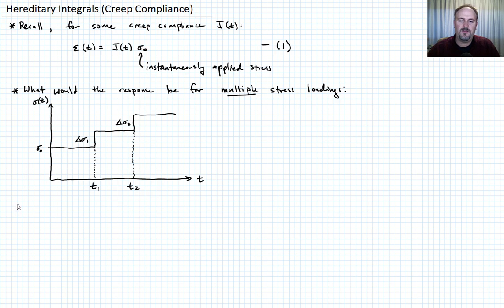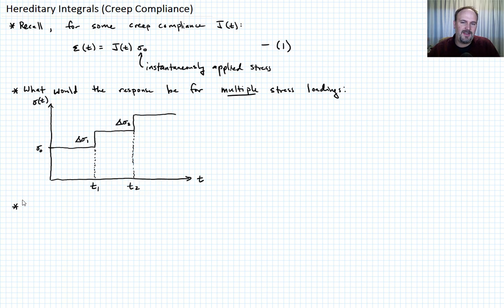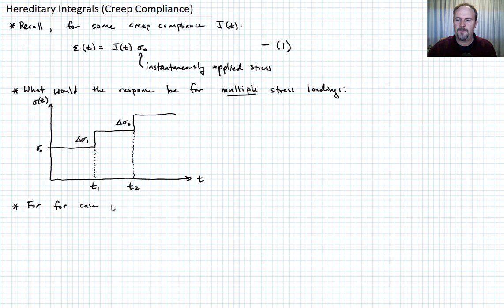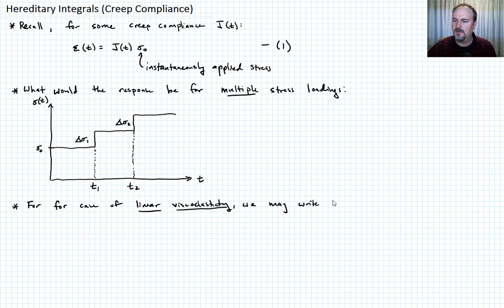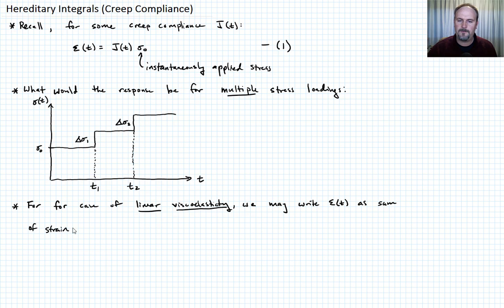We are only interested in linear viscoelastic materials. That doesn't mean their stress-strain curves are linear. What it does mean is that we can write the strain as the sum of the strains produced by each loading. So for the case of linear viscoelasticity, we may write epsilon of t as the sum of the strain produced by each load.